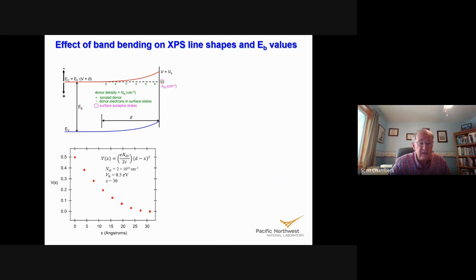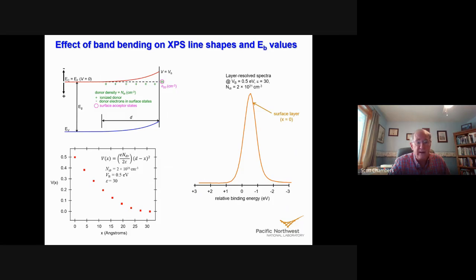Okay? Well, let's suppose that I'm measuring this very surface with photoemission. What am I going to get? Well, I'm going to have one binding energy right at the surface. And so if I have a nice sharp core level, it's going to give me a binding energy that is somewhat low because the bands are bending up. And relative to 0, it's going to be about a half a volt lower in binding energy relative to the bulk Fermi level. If I go down one layer, I'm going to get a slightly lower binding energy. The intensity will also be lower because it's attenuated, because it's a little bit deeper. And same thing with the third and the fourth and so on, until I reach the bottom of the depletion width. Okay, so down at x = d, the deepest level in this material is going to have the lowest.